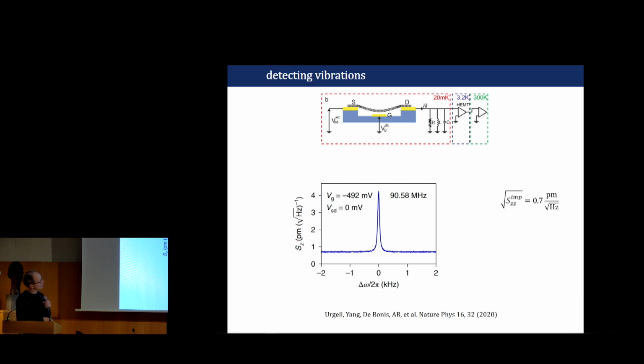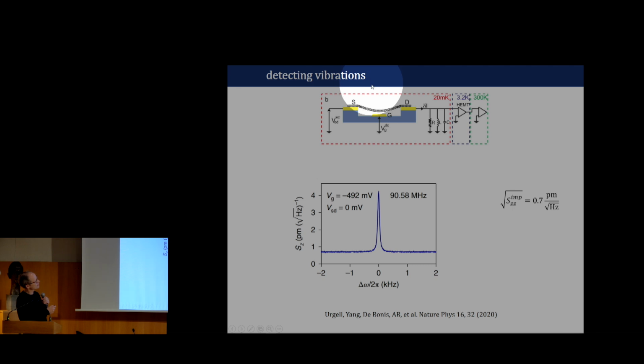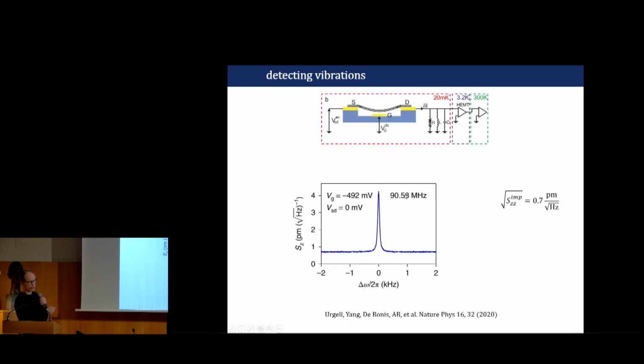So how do we detect the vibrations? We detect them by measuring the current noise through the nanotube. And we use the nanotube as a field effect transistor, and we use the capacitance between the gate and the nanotube. And in this way, we can measure the noise of the displacement, which corresponds to the fundamental mode of the nanotube, which is at about 90 megahertz.